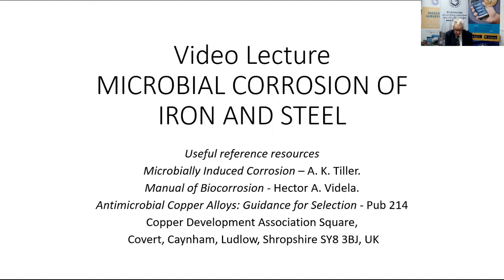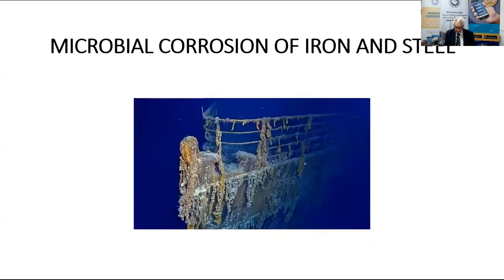As a direct result of the attack of the microbes, which are reducing her iron at an estimated rate of 0.3 grams per square centimetre of area per year, it is estimated that within the next 100 years, I have seen other dates, or so, the steel remains of the Titanic will have completely disappeared and turned into a mountain of ferrous and ferric hydroxide at the bottom of the ocean, eventually to disappear in the abyssal mud. Here's a photograph of her bow. You can see those rusticles hanging from the side. What happens is that they eventually get too heavy and fall off, leaving a new surface for the bugs to attack. And that ship, as I said, will virtually disappear in 100 years.